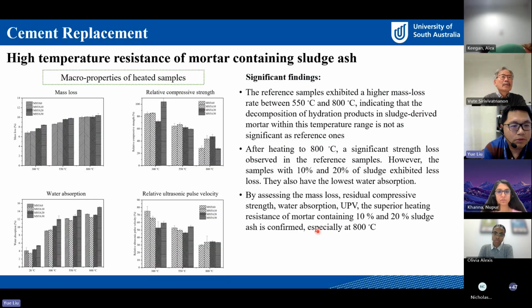As we confirmed the sludge can promote the formation of aluminum-bearing phases, and because some of these phases may have excellent high temperature resistance, I then studied the high temperature resistance of mortar containing sludge ash by assessing the mass loss, residual compressive strength, water absorption, and the UPV. I found that the superior heating resistance of mortar containing 10% and 20% sludge is confirmed.